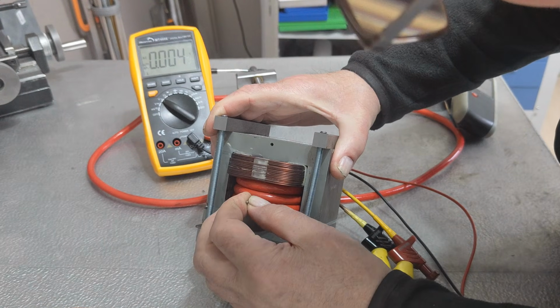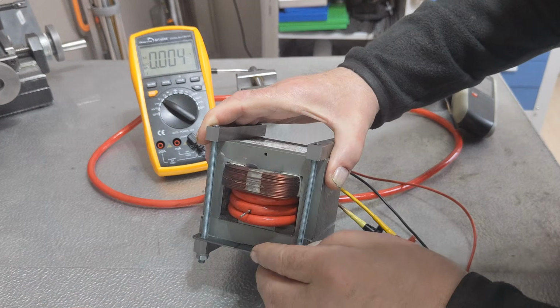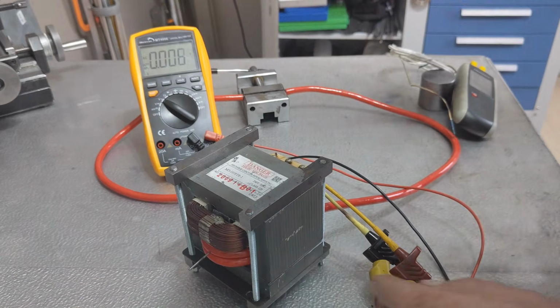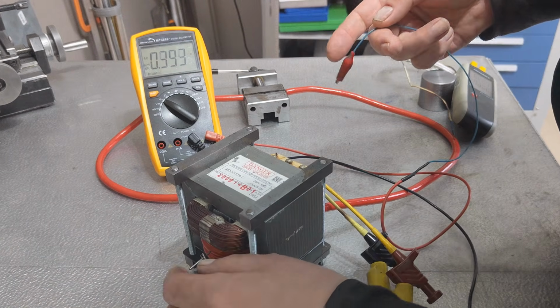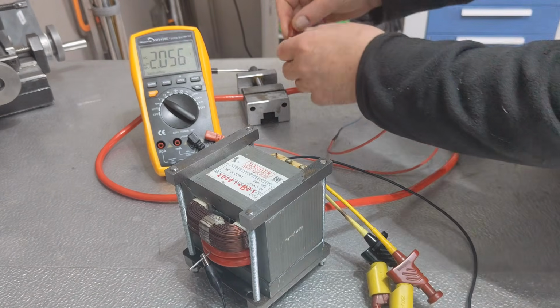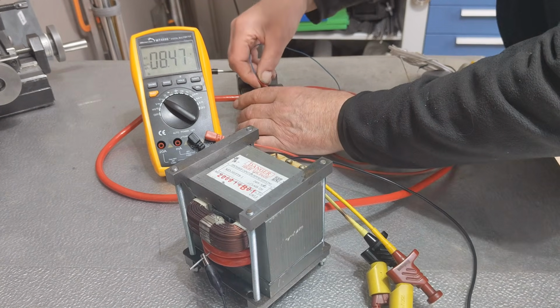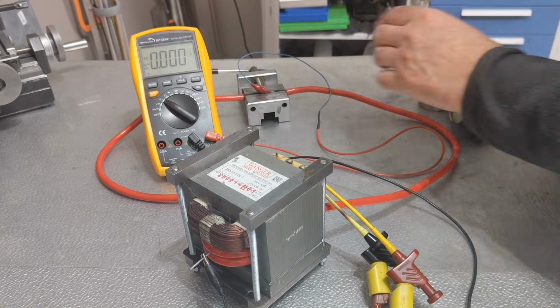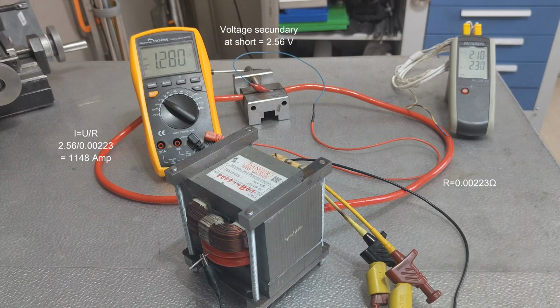Here I perform what could best be described as a spinal tap on the winding. With the secondary short-circuited, I measure the voltage between one end and the freshly punctured midpoint of the secondary winding. The total voltage turns out to be no less than 2.56 volts. According to Ohm's law, that corresponds to a secondary current of well over 1100 amps.